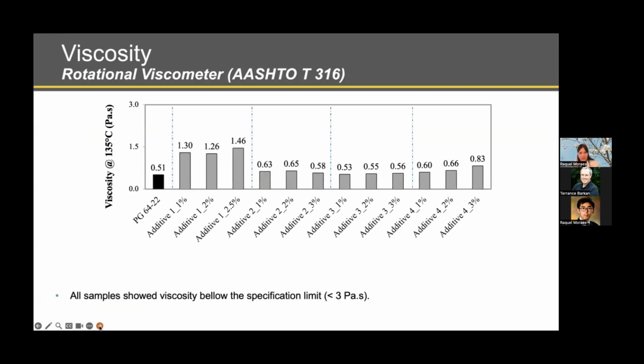First results that we have here to present are the viscosity. That was measured with a rotational viscometer. You can see here in black the neat binder, meaning the base binder evaluated in the study without any graphene in it. Then on the following columns in gray, you can see the binder modified with each graphene product. For all the additives at the 3 evaluated dosages, the final viscosity was below the specification limit of 3 Pascal second, which is a very positive result.